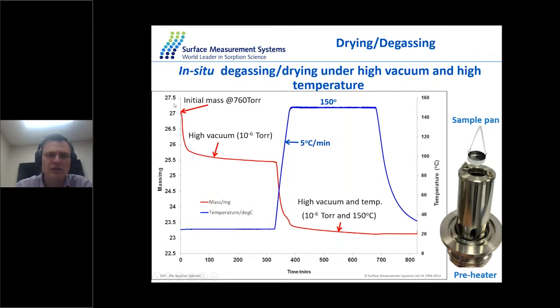So I will give some examples. Here we look at the in-situ drying curve for outgassing of Mof 74 at room temperature and high temperature. Initially we load the material at 1 bar, pull high vacuum, and let it outgas at 25 degrees. What you can see, you get a certain mass loss, a straight line. But what we did, the system allows us to increase the temperature to 150 degrees. So what you can observe here, you get an even bigger mass loss. So now we can compare. This plot demonstrates the differences in outgassing, which might have a big impact on your adsorption capacity. Because in both cases you can see the line is flat, but with outgassing at higher temperatures, you can completely empty the pores, so you can remove all these physisorbed molecules, which is not possible using just ambient temperature.